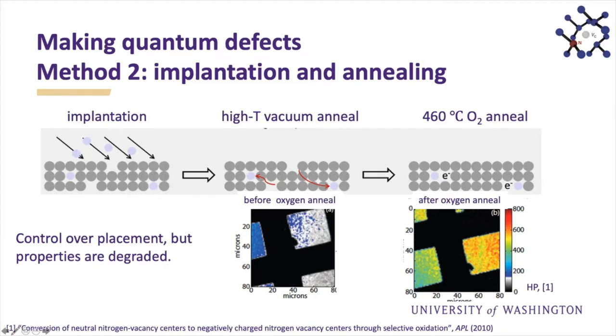The way we make them to have the most control is to do implantation and annealing. In this case, I'm using, again, the example of nitrogen vacancy centers. We take our diamond, we implant nitrogen ions where we want them. We can have them, for example, going through a grid. And then we do a very high temperature vacuum anneal. Afterwards, what happens is that the nitrogen substitutes for a carbon site, and also the vacancies that formed due to knocking out carbon atoms can migrate to the nitrogen and form that nitrogen vacancy center. And here you can see after implantation, we've only formed these nitrogen vacancy centers where those ions have implanted into the diamond.